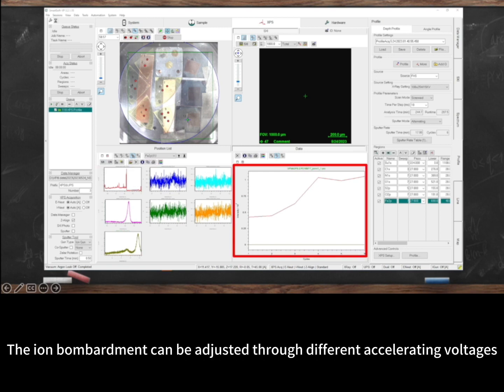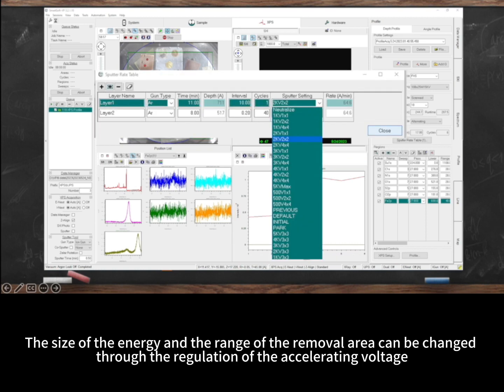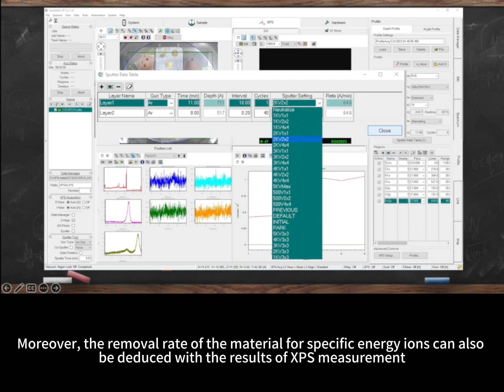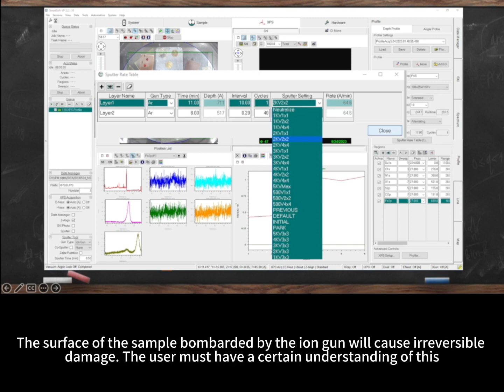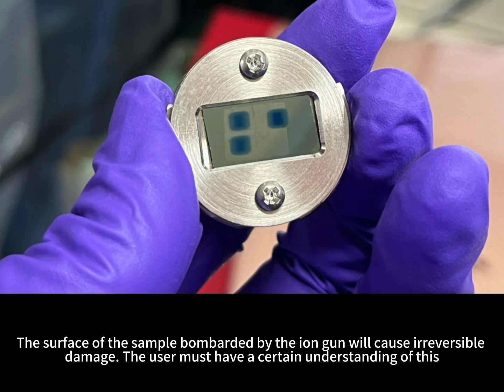The ion bombardment can be adjusted through different accelerating voltages. The size of the energy and the range of the removal area can be changed through the regulation of the accelerating voltage. Moreover, the removal rate of the material for specific energy ions can also be deduced from the results of XPS measurement. The surface of the sample bombarded by the ion gun will suffer irreversible damage. The user must have a certain understanding of this.